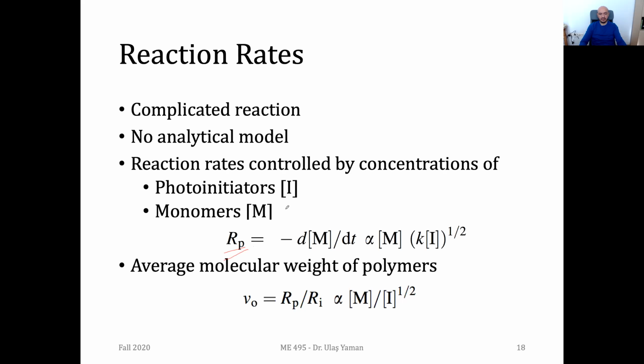And we have two important variables. The first one is the amount of monomers and the second is the amount of photoinitiators. If you look at the reaction rate here, it simply depends on the consumption rate of monomers. So we can say that if you put too much monomer in your composition, then your reaction rate will be higher. And as you see here, it's directly related to the amount of material you are consuming in unit time. It's also related to some other parameters, but the most important parameter here is the amount of monomers consumed in unit time.